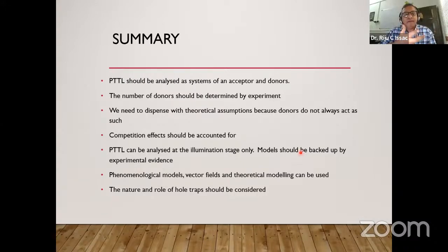Is it possible to engineer the spectrum by adding point defects or introducing some defects to the material? Is that the way that you do to change the variation? Yes, it's possible. For example, in aluminum oxide, when you dope aluminum oxide with carbon, you generate a large number of F centers, and those F centers will emit at 420 nanometer. Now, when you double dope carbon and magnesium, you still get emission at 420 nanometer, but if you anneal the sample, you force the emission to the F+ centers at 330 nanometer. So you can treat the material by doping or annealing it or heat treatment, and that will modify the emission band.